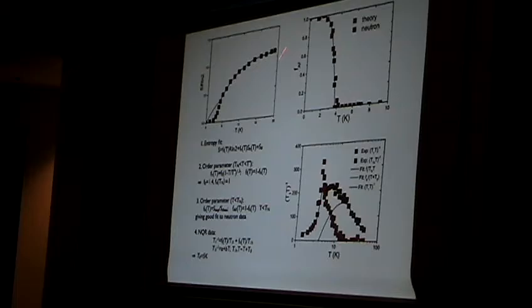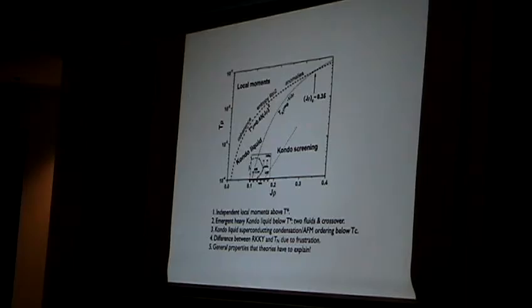We further analyzed spin-lattice relaxation rate and we found the heavy component has actually a spin-lattice relaxation formula 1/(T1T) proportional to T plus T0, which is from some critical fluctuation of 2D spin liquid. Therefore it's saying that in the quantum liquid we can have some critical fluctuation and then it condenses into a superconducting state. We also did analysis for antiferromagnets and what we found is possibly the same. This is preliminary, so we won't discuss that.